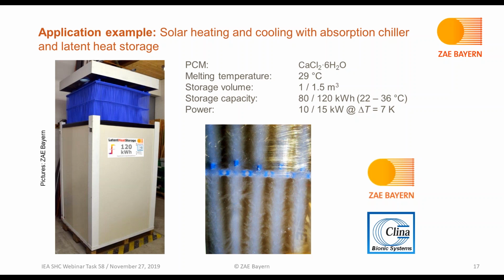So what is the special feature of this type of storage is we are using a so-called capillary tube heat exchanger, which is immersed in the liquid PCM. So the blue capillary tubes are made from plastic to account for the corrosive properties of the salt hydrate. And the picture in the middle shows the PCM crystallizing on the surface of these capillary tubes.